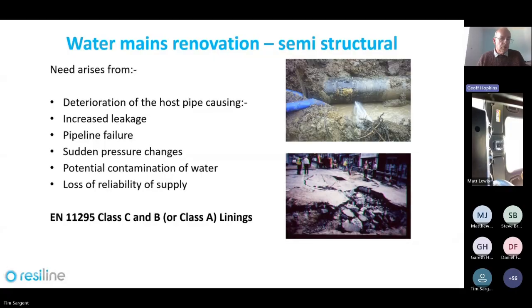So Class B semi-structural lining is an adhered lining, which is generally used in larger diameter pipes. Class C semi-structural linings are standalone linings which are not dependent on adhesion to the host pipe wall, where the hoop lining that you've applied has sufficient hoop strength to resist vacuum or external groundwater pressures on the lining. And these linings are fundamentally installed to bridge holes and defects that appear through the pipe wall, and relatively thin linings can withstand quite large corrosion holes behind them. The lining acts as a clamped plate. Something like a 3mm lining can quite happily resist up to 8-10 bar operating pressure.